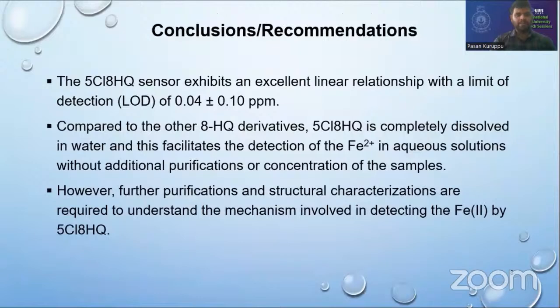The conclusions and the recommendations. The 5-chloro-8-hydroxyquinoline sensor exhibits an excellent linear relationship with a limit of detection of 0.04 plus or minus 0.1 parts per million. Compared to the other 8-hydroxyquinoline derivatives, 5-chloro-8-hydroxyquinoline is completely dissolved in water, and this facilitates the detection of Fe2+ in aqueous solutions without additional purification or concentration of the samples. However, further purification and structural characterization are required to understand the mechanism involved in detecting Fe2+ by 5-chloro-8-hydroxyquinoline.